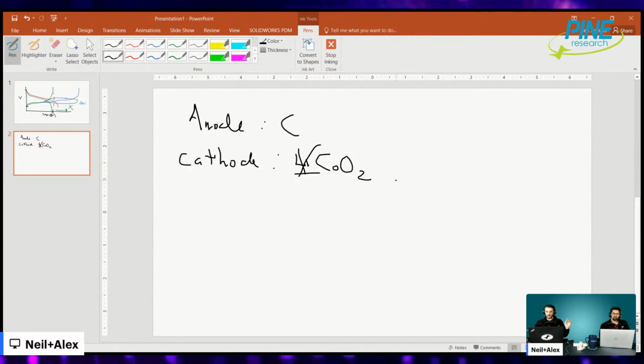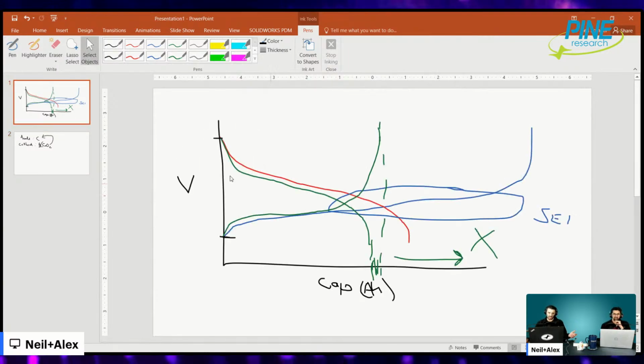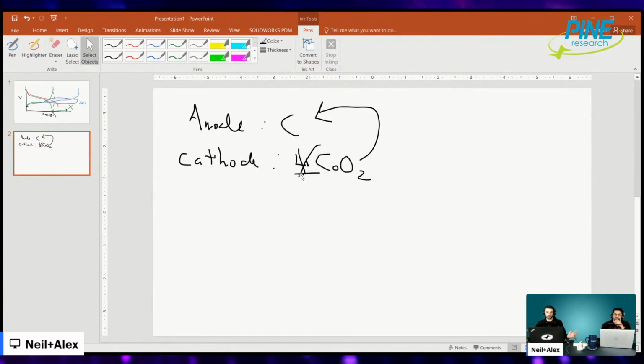And so to make the SEI, the lithium ions will go from the cathode to the anode, and part of that current will be this plot here. You'll get that kind of SEI forming. Okay. And so the only way you're going to do impedance on that first scan is if you want to study the initial SEI formation, which you might, fair enough. But if you're trying to study the fundamental application of the battery and the cathode, the anode performance over time, and not the initial procedure, then you're going to want to skip those first couple of steps. Right. So there's that. Okay.